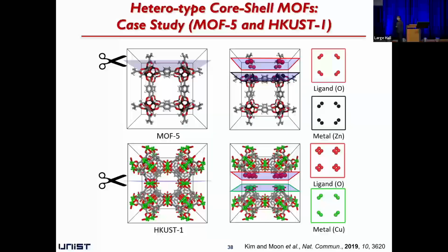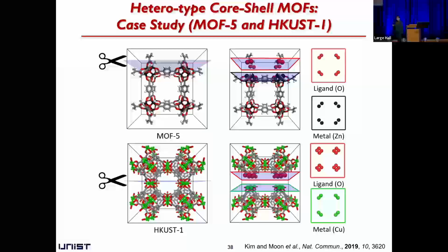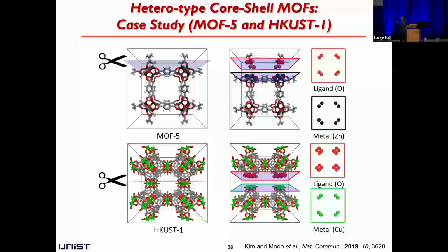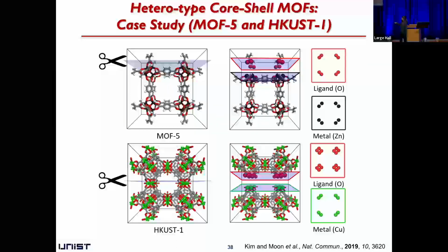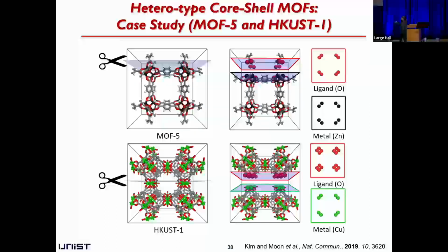And next, we need to consider the chemical connection point. Chemical connection point means ligand position and metal position. So if you make a slice through the coordination bond between the oxygen of a carboxylate and the metal from the SBU, then if you see the cross section, we can see the position of a ligand and metal. This can be the potential chemical connection point with the next metal organic framework at the interface.